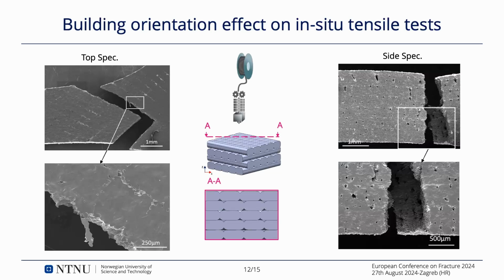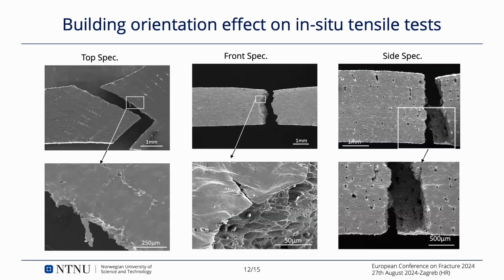These are fracture pictures, so of course the pores enlarged and deformed, but also in undeformed condition, it was quite clear that there were a lot of pores. And here the fracture is quite quick because it's sufficient to follow an alignment of pores, and that's why they tend to fail earlier. And finally, we have the front specimens in which we can see some classic signs of ductile fracture. So we have quite a lot of elongation before fracture, localized area reduction, the dimples in the fracture surface. And we also saw that there are a lot of inclusions that probably come from the powder atomization process, and they stay in the specimens and they favor the void nucleation.